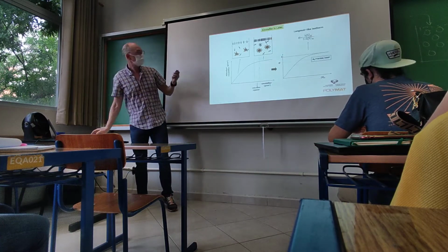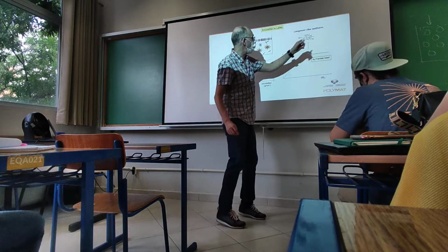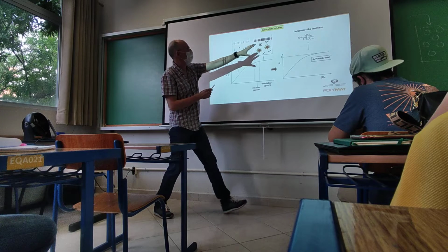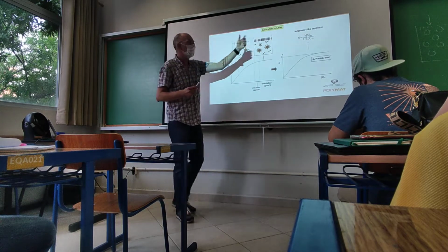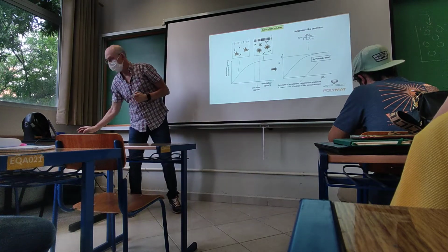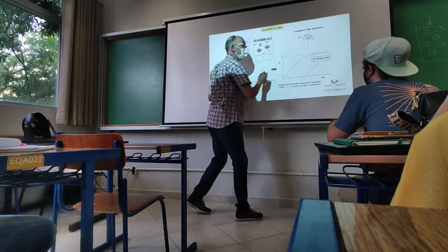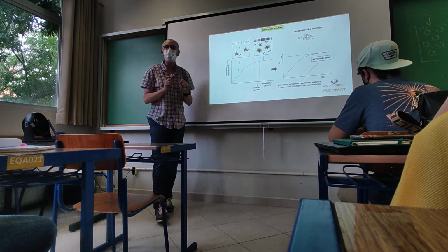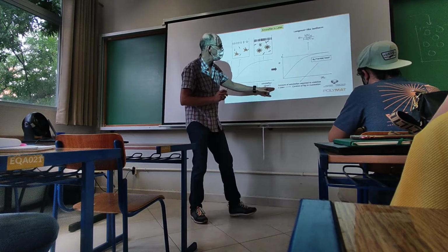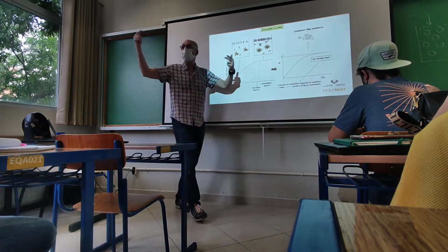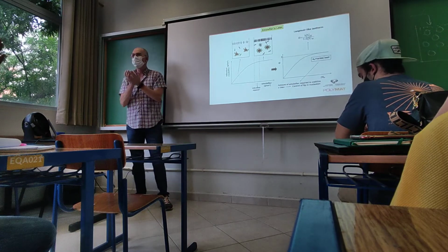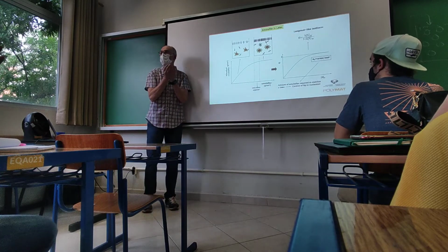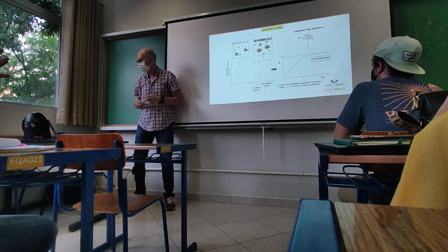So these are the curves that you may obtain by doing this analysis, which give a Langmuir-like isotherm from which you can calculate another important parameter of the surfactant, which is the packing area. It's called packing area, which basically means the area that the surfactant molecule or mole can cover. Okay? And this depends on the nature of the polymer that you have. Okay? And of course the nature of the surfactant.